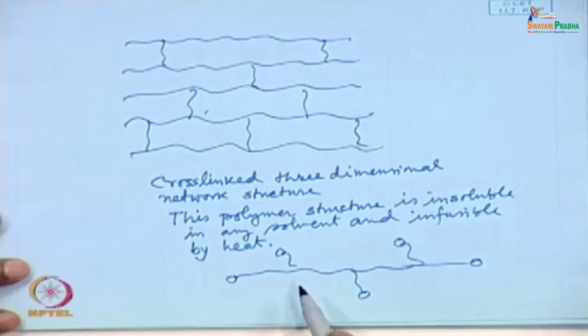I give you a concrete example of phenol formaldehyde resin. There are two ways of phenol formaldehyde resin synthesis. First day I showed you how phenol and formaldehyde condense. A stage resin, do you remember? A stage resin, B stage resin, C stage resin, of which A stage is linear, soluble, thermoplastic. B stage is branched, soluble, still thermoplastic, and C stage is the final stage, a cross-linked thermoset stage. So, we have to stop the polymerization at the B stage. Maximum you can go up to the B stage. Then you take that B stage polymer for making any laminate, for making any composite.